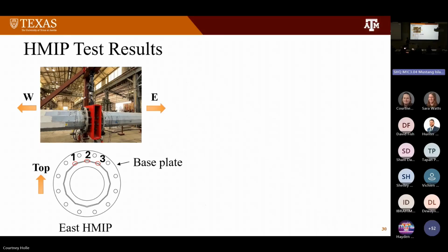I'd like to share some of our results regarding the HMIP test and repair. We focused our test on 2 posts, 6 bands. However, most of them have undergone only 1 repair. The East HMIP band 2 has undergone 5 repairs. This allows us to share the effectiveness of each repair attempt.